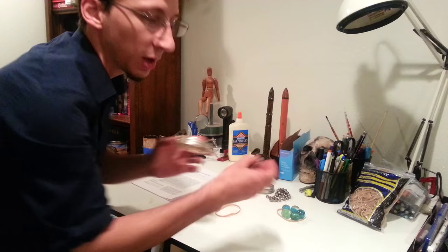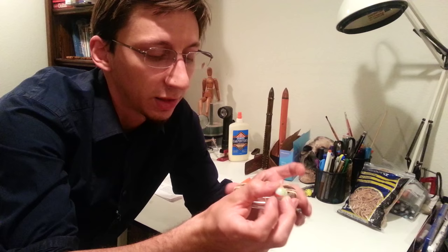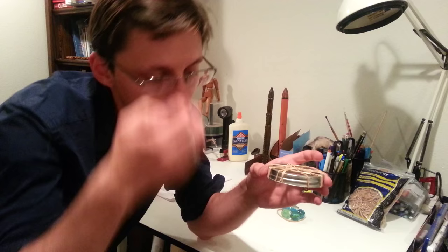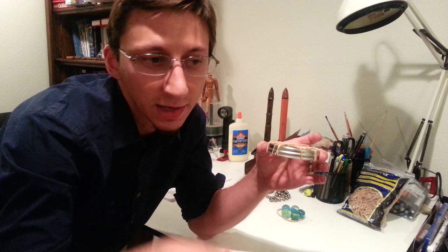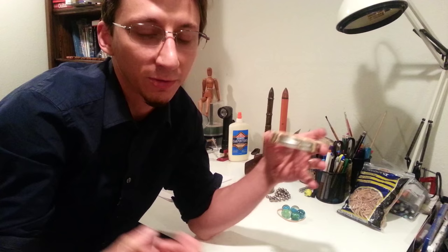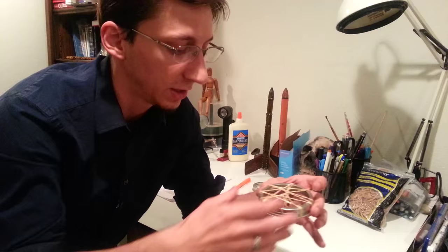Now, I assumed that carbon dioxide was just a little bit bigger than the helium, well, maybe a lot bigger, but bigger than the helium, and it would follow the same properties. But actually, the carbon dioxide has many more interactions with the latex surface, and some of them are entropy-driven, sort of hidden down underneath Henry's law. There's actually more ways for the gas molecules to be absorbed into the surface than there are for them to be out of the surface. It's kind of like it's got little hooks on it. Now, this is not literally true.